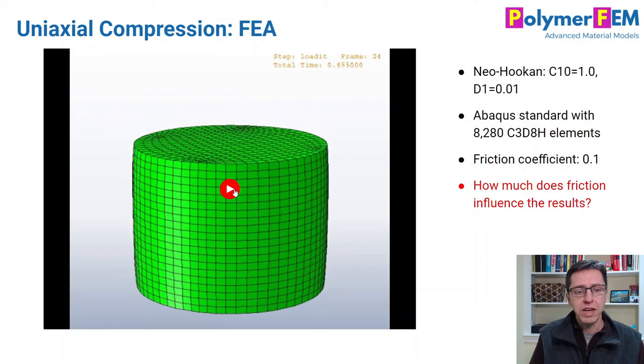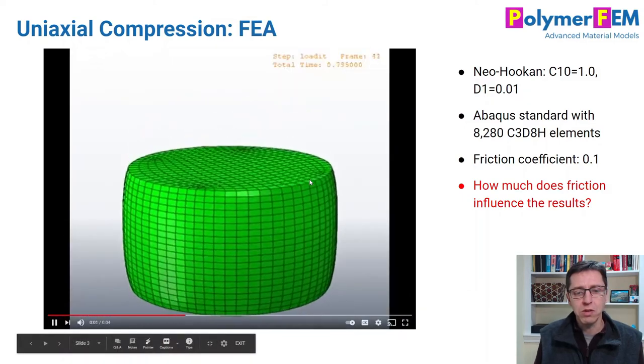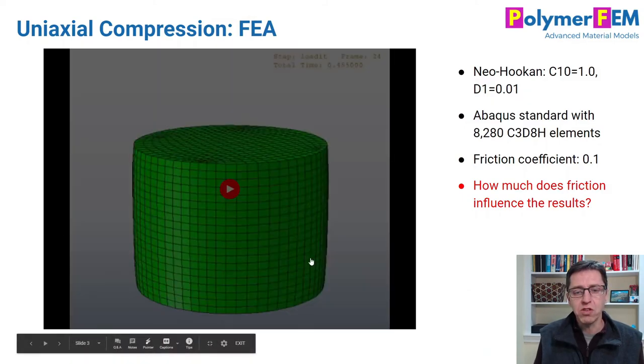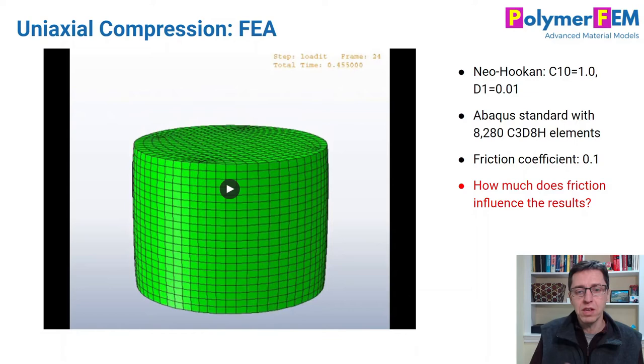Here's a simulation that I performed. It turns out it's difficult to prescribe a given friction coefficient experimentally, so it's often easier to study this using finite element simulations where we can select the contact conditions and friction coefficients anywhere we like. As I compress the specimen, you can see it does not stay straight as a cylinder anymore — the sides clearly barrel out during the compression. That's also what happens experimentally. This was a basic simulation of a Neo-Hookean hyperelastic material with a friction coefficient of 0.1.